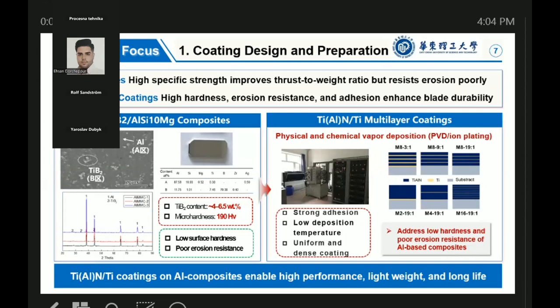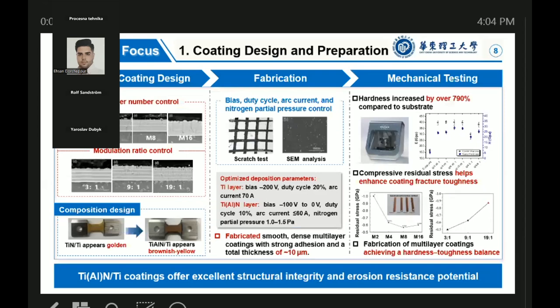and long service life. And we designed coatings with 4 layer numbers and 3 modulation ratios to optimize the stress-toughness balance. Each coating had a total thickness of 10 micrometers. After optimization, smooth, dense, and well-adhered coatings were obtained. All coatings showed over 4 times the substrate hardness, and fracture toughness increased with both layer number and modulation ratio. Also, residual compressive stress further improved the toughness. Overall, the optimized coating exhibits excellent integrity and erosion resistance potential.